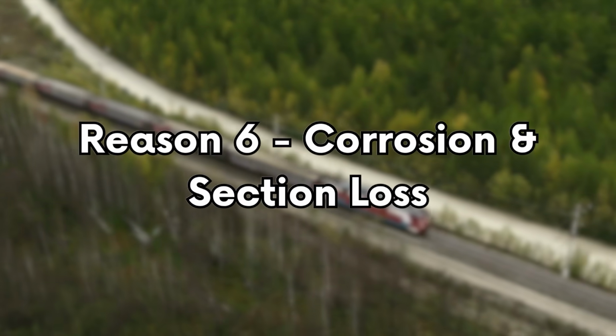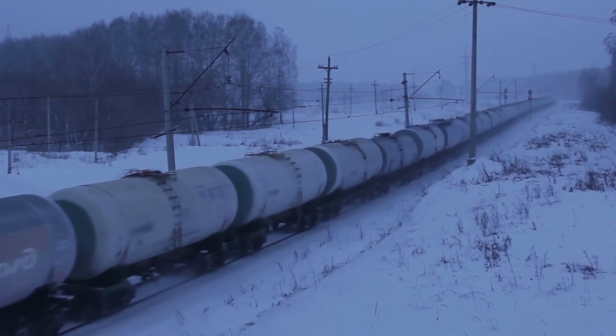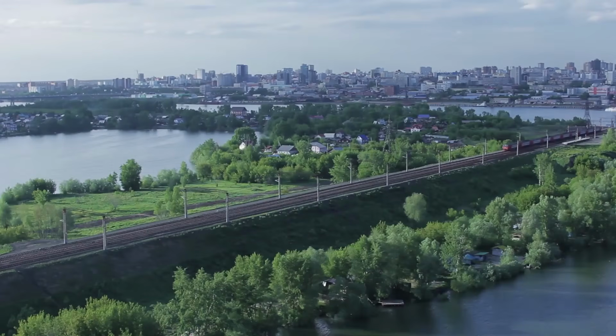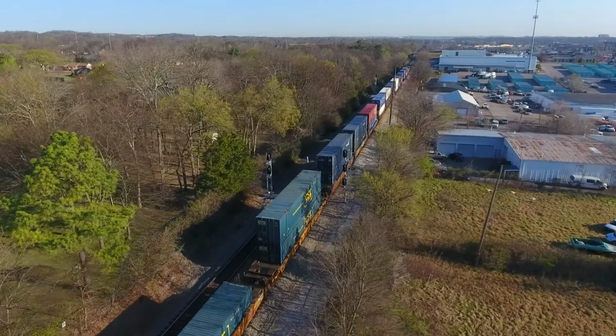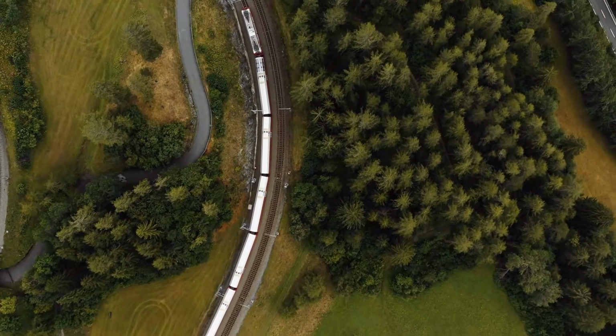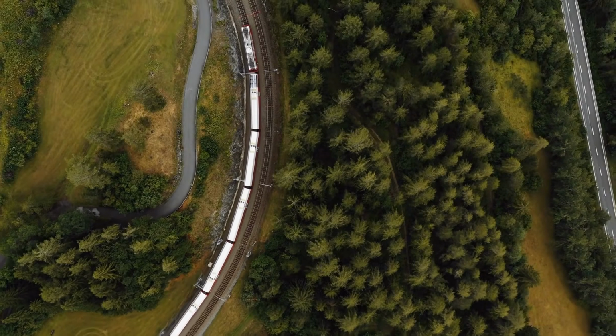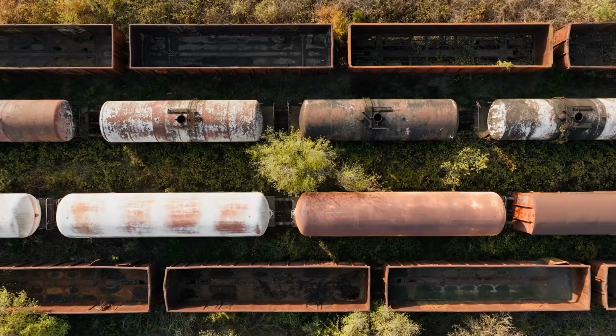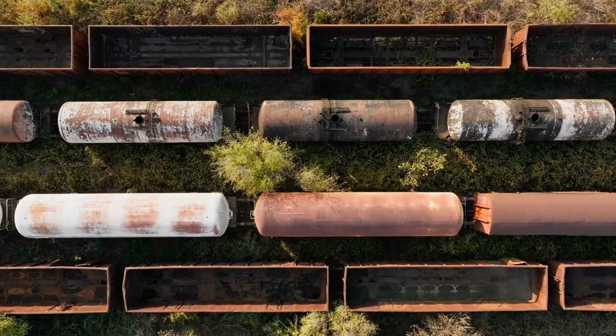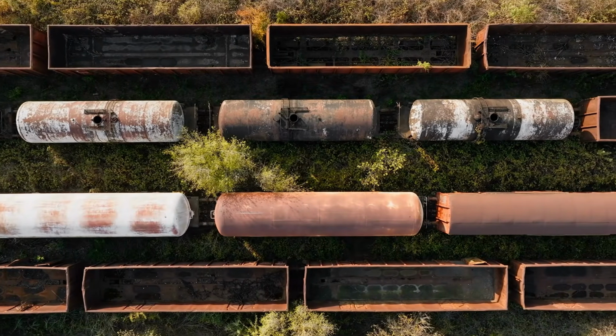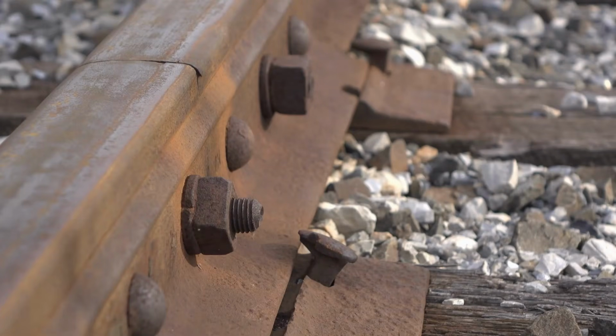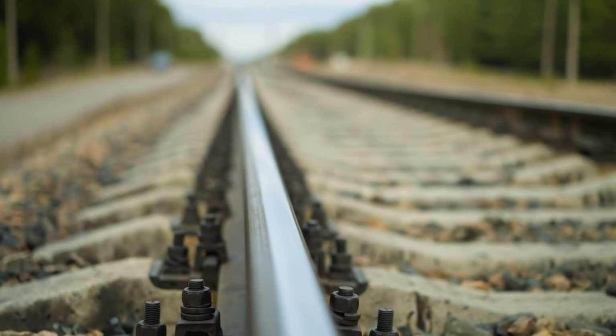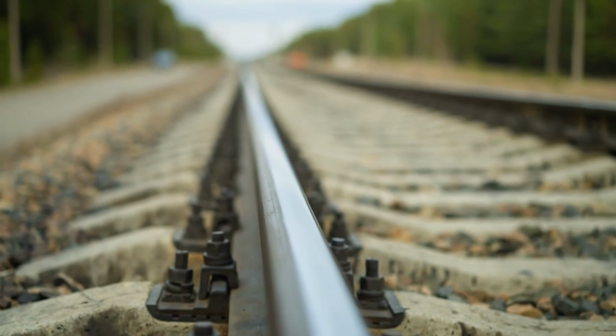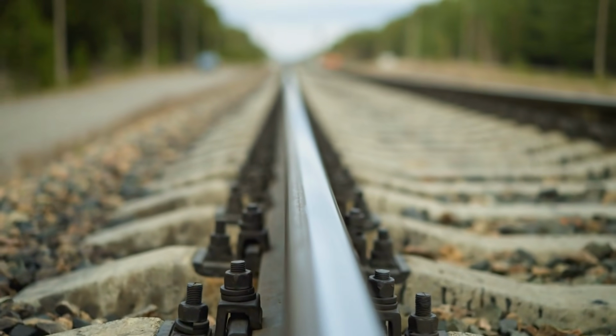The environment in which rails find themselves can also be the cause of a rail break. The railway passes through various environments and experiences all different weather, so it shouldn't be a surprise that nature gets its own back at some point. Corrosion and pitting both lead to the loss of material in the rail, sometimes known as a loss of section. While corrosion can be across a wide area, pitting tends to be more focused but deeper, leading to a stress riser where cracks can begin.